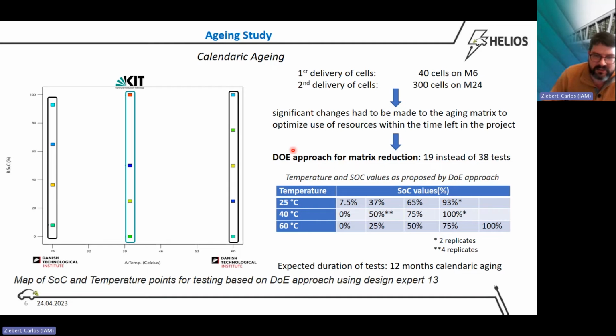And then we decided to do a design of experiment approach, which is shown here. So the matrix for the calendaric aging is reduced by looking for the correlation of the different parameters. So in this case, temperature and SOC, and doing some kind of sensitivity analysis, which parameters are most important in which regions. And then we were able to reduce the matrix from 38 to 19 tests only.